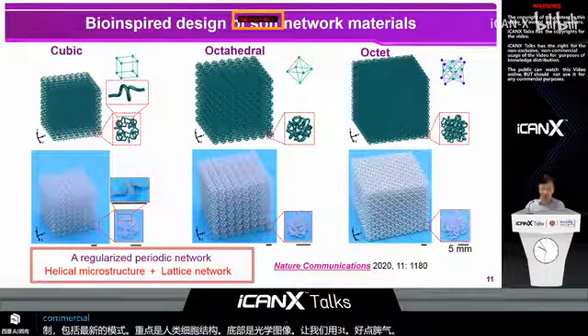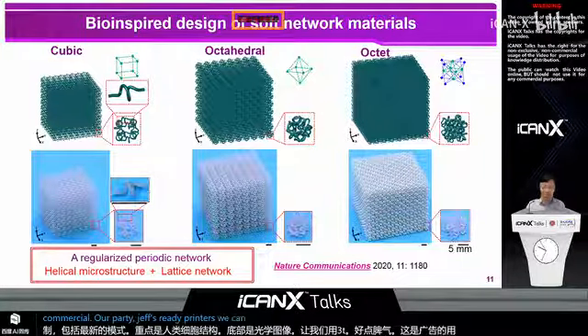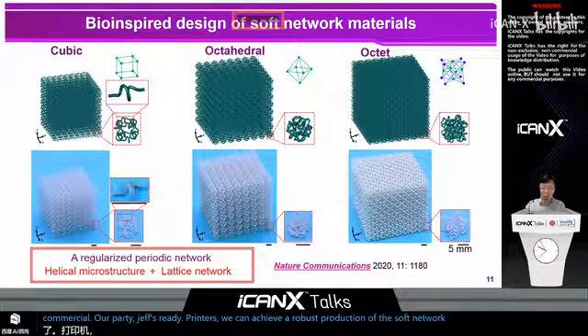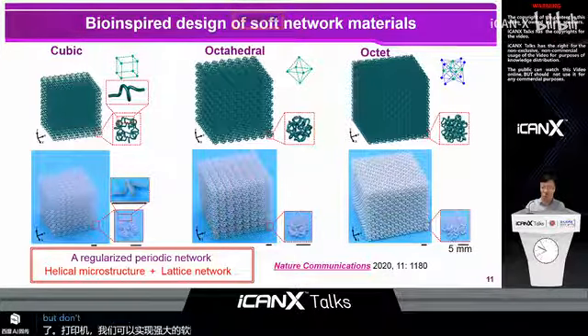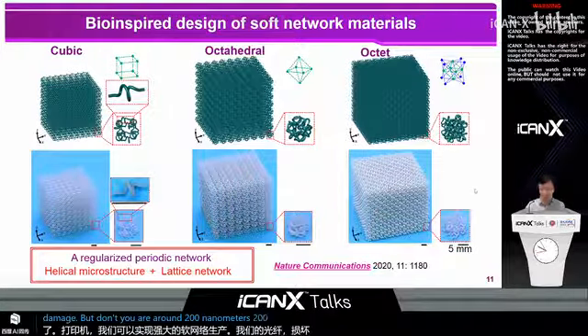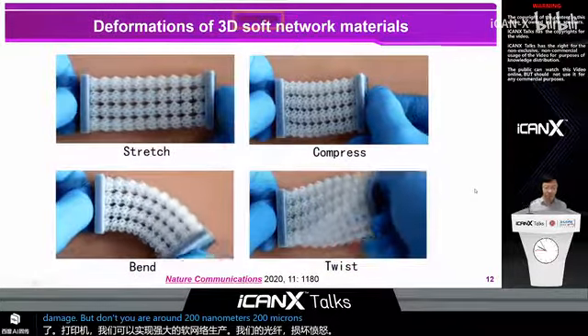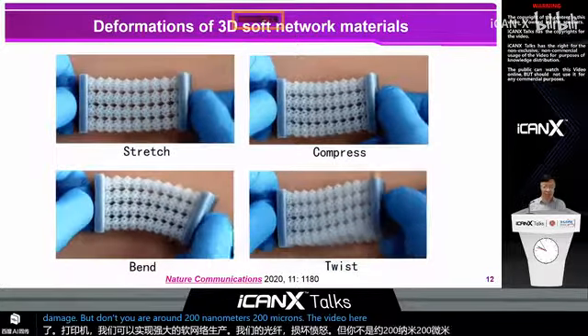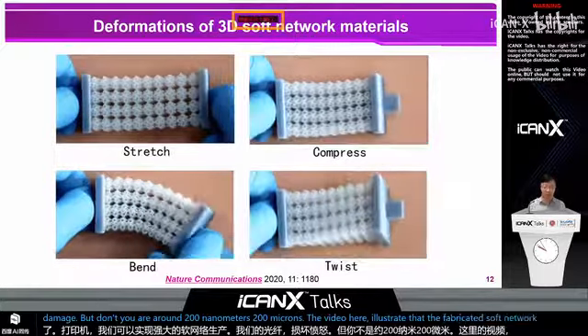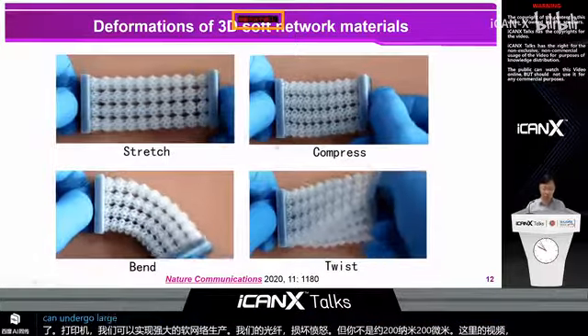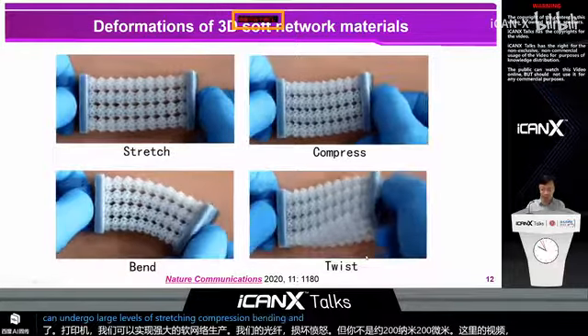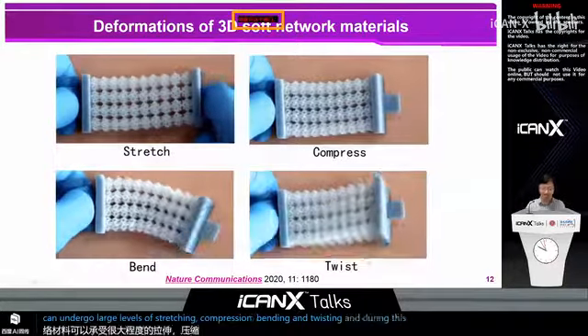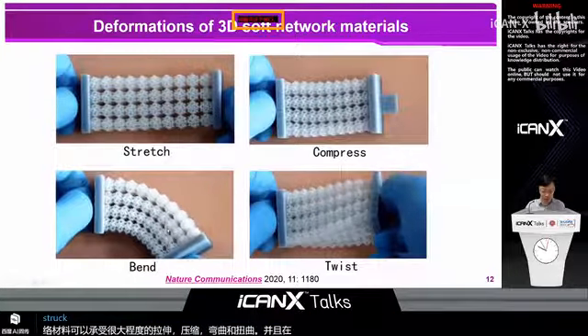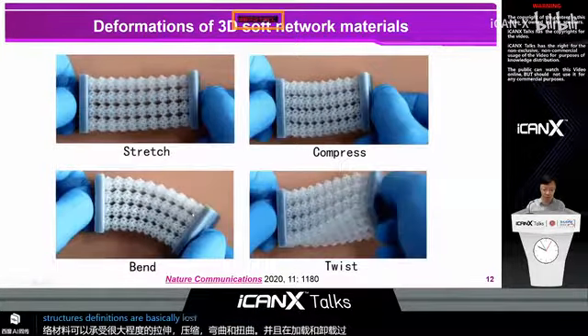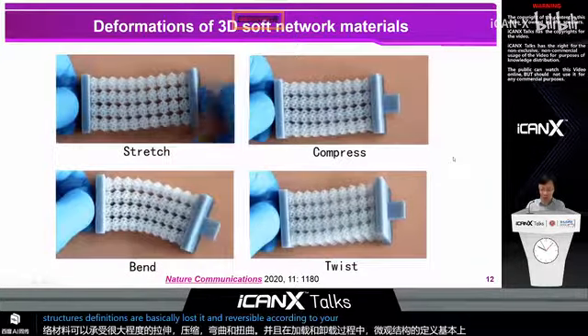So here, with the use of the commercial PolyJet 3D printer, we can achieve a robust production of the soft network materials with a fiber diameter down to around 200 microns. The video here illustrates that the fabricated soft network material can undergo large levels of stretching, compression, bending, and twisting. And during this loading and unloading process, the microstructure deformations are basically elastic and reversible, according to our mechanics modeling.